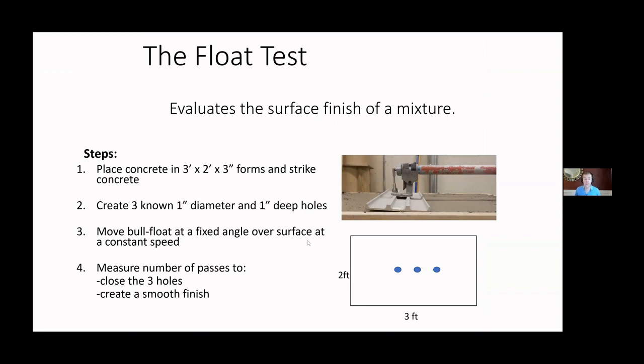Now, this test actually is a 3-foot by 2-foot form that's 3 inches deep. You fill it full of unconsolidated concrete, you strike it off, and then you start to finish it back and forth. Oh, I left one point out. You actually form 3 1-inch diameter holes that are 1 inch deep. Why do you do that? Because when you strike the concrete, you want to simulate aggregates being plucked out of the surface. And we're going to measure how many passes it takes to finish the surface, to smooth the surface out and to close the holes up.